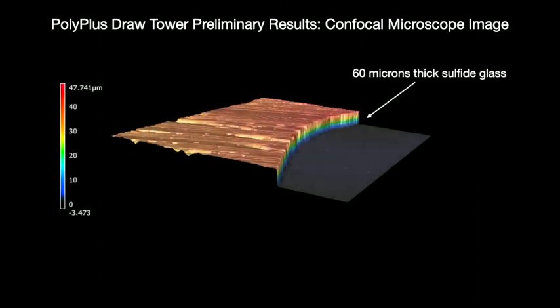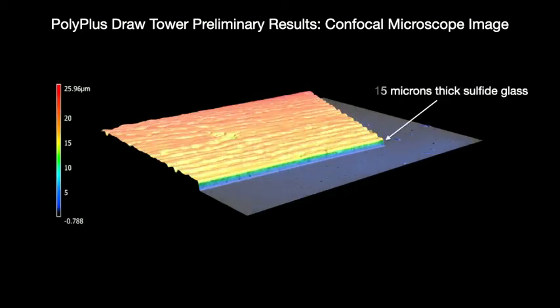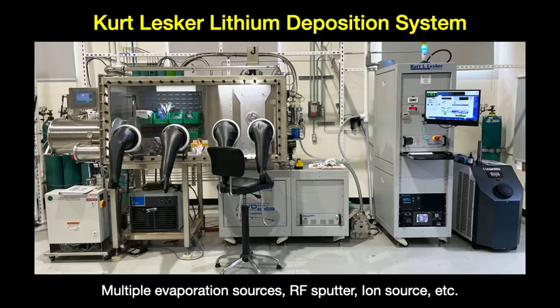And I can show you some of the preliminary data on drawing glass. We've been drawing glass now for just about a month. And you can see that we can draw 60 micron glass. And even more impressively, we have drawn glass as thin as 15 microns. So this is as thin or maybe thinner than polymeric separators and much stronger, right? And this is, again, a single ion conductor.